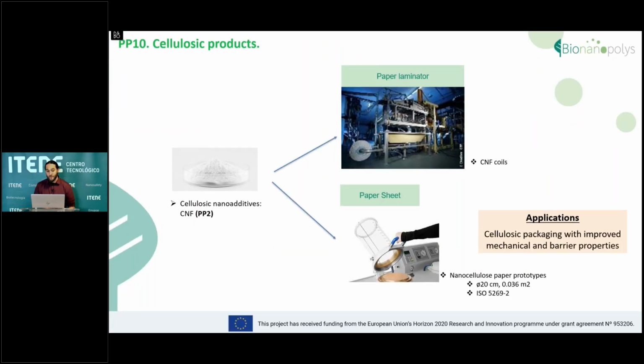Regarding cellulose products in pilot plant 10, these cellulose nano additives can be mixed in mass with paper pulp using our standardized paper prototype machine to obtain a disc of 20 centimeters in diameter, or could be laminated in paper coils with the CTP pilot plant. Then with this, we expect to have paper packaging with improved mechanical and barrier properties.